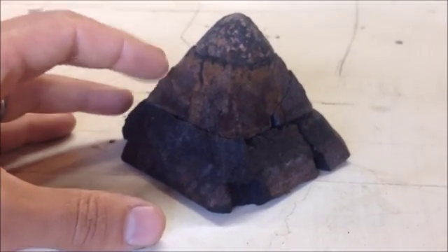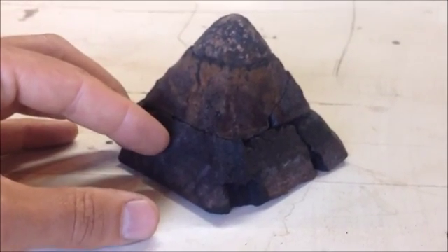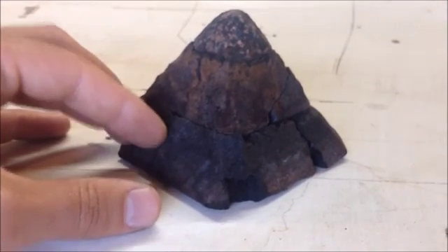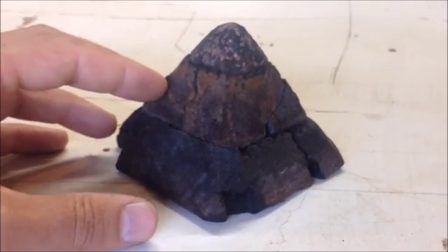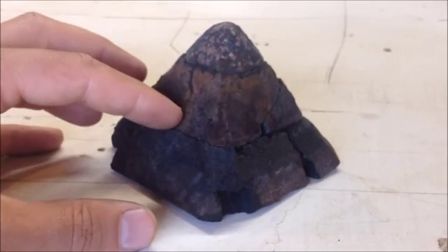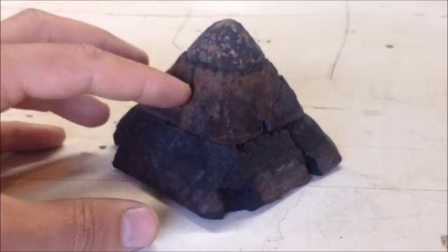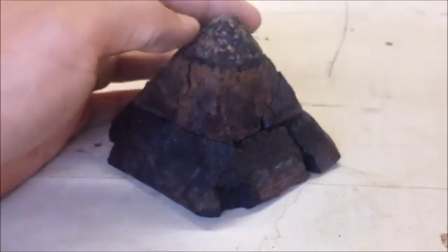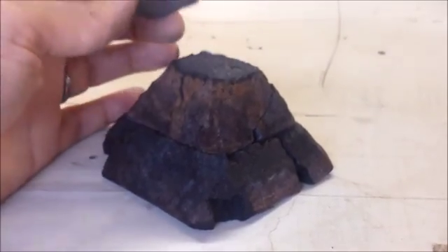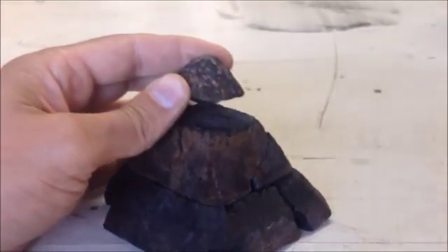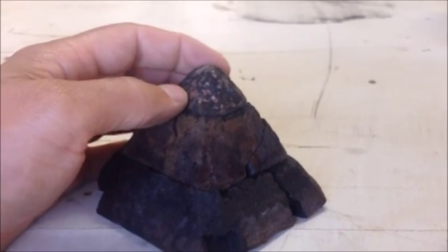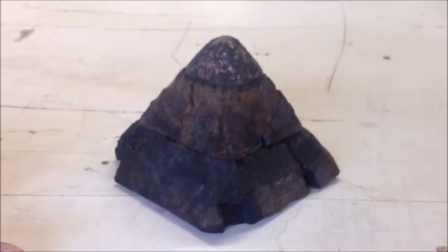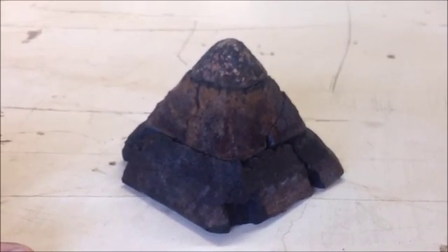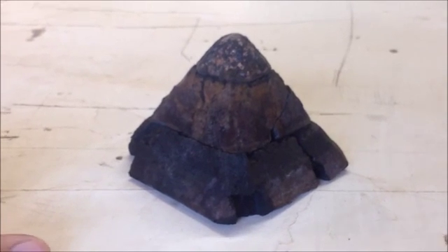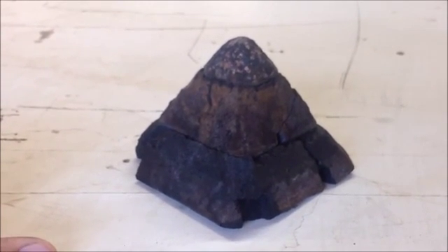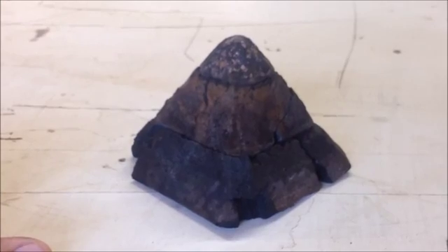And the only problem I had here is I added too much iron and not enough slag, so the slag couldn't absorb as much iron sulfide as I added, so it essentially formed an iron sulfide mat here, which is okay because most of our precious metals and our base metals ended up down here in our copper button anyway. So it was a successful processing of the mat from the first smelt, and we got away from roasting any of our sulfides.